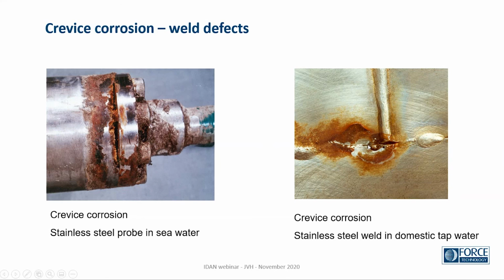But also a weld defect like this one, stainless steel welded without full penetration, gives us a crevice which has started corrosion. And this is in Danish domestic tap water. We have salt enough for causing this problem.